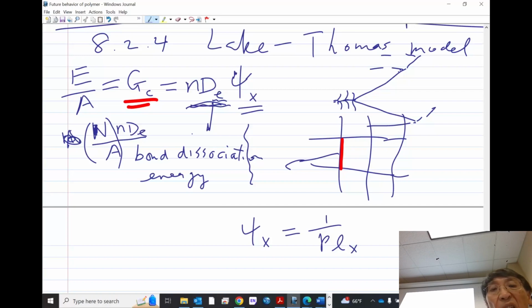And may I add a little symbol to remind myself, it's not n, but nx, right? Because this strand has a length of nx, involving nx repeated units. X just stands for cross-linking. And this size, remember, the so-called end-to-end distance, we call it the size, is of course the square root of nx, and in strict units you may have the characteristic constant times the bond length.